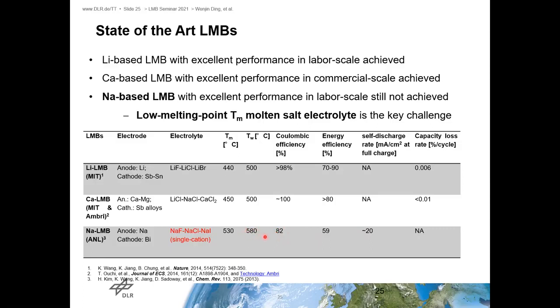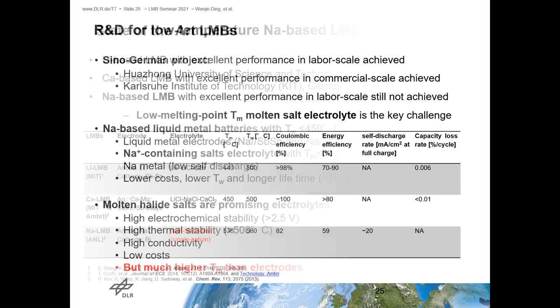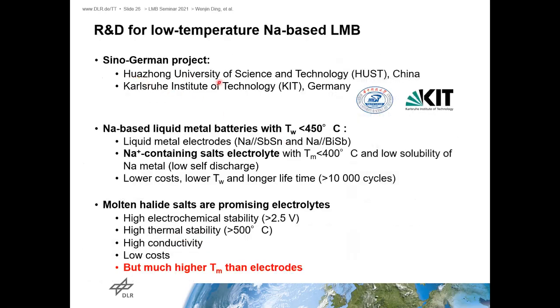From our heat storage experience, we think if the temperature is higher than 550 degrees C, we need to use expensive alloys. So in our project with our partners in China and Germany, the Huazhong University of Science and Technology and KIT, we wanted to develop a low temperature sodium-based liquid metal battery. Using sodium can reduce the battery cost, and low operating temperature can reduce the cost of the structural materials.